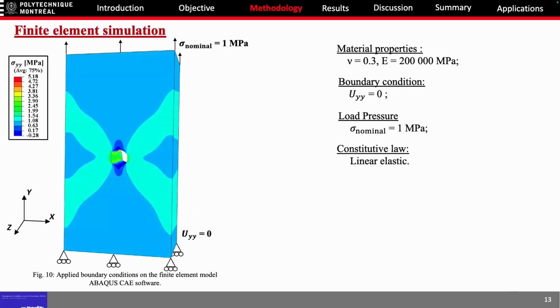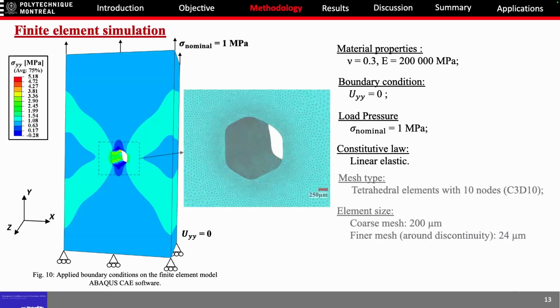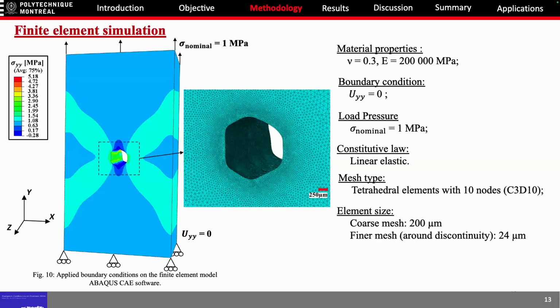This is one of the specimens, and we applied the appropriate boundary conditions and nominal stress with the material properties of stainless steel, and the constitutive law is linear elastic. Tetrahedral elements were used, and the bulk model was meshed with 200 micron elements, and a finer mesh around the vicinity of the discontinuity.